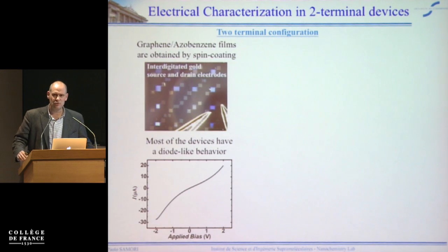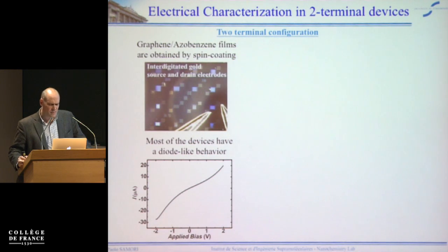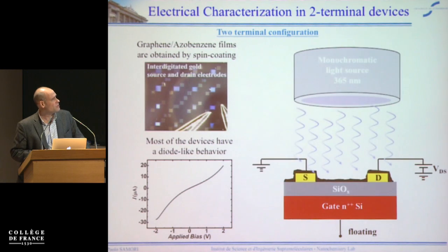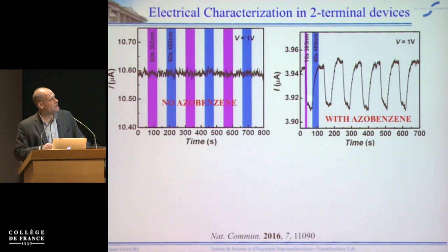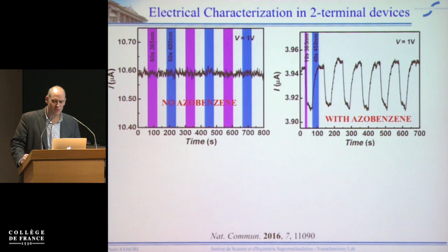And now my idea was to use this kind of bicomponent ink to create some photo-switchable electrical devices. We took this ink and deposited it in between two interdigitated electrodes of a transistor, and then you can in situ do irradiation either with UV or with visible light, and you can see that there is a nice response of the current through the junction due to the irradiation at different wavelengths. If you do the same with graphene ink that has been produced in the absence of azobenzene, so in pure NMP, there is not at all a response to the light stimulus. So the presence of the azobenzene plays a role in changing the current with a photochemical stimulus.